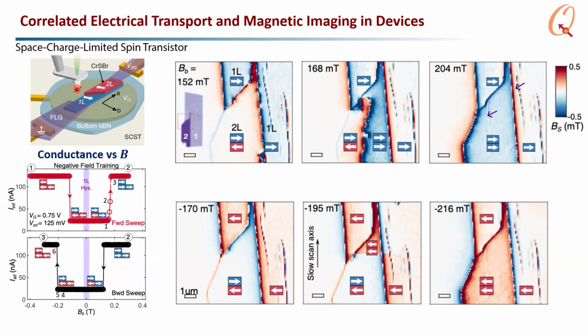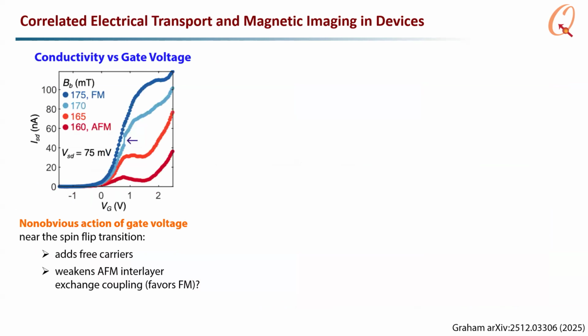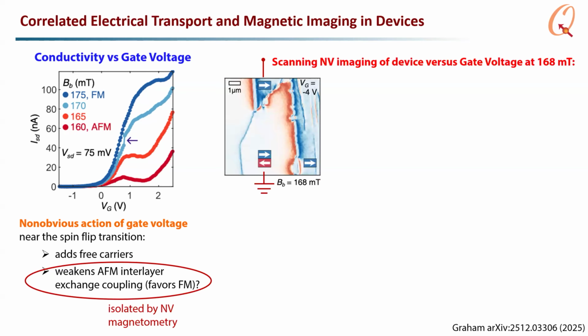So this labeling of the states at all different values of the conductance is unique. We get that from NV center magnetic imaging. So you might say this is pretty self-explanatory, but there are signatures in the transport that are not that obvious. Okay, so we can take a look at the conductivity versus the gate voltage, and it just goes up. And then you might say that the only thing the gate voltage is doing is adding free carriers to the channel. But it's doing more than that, because I can